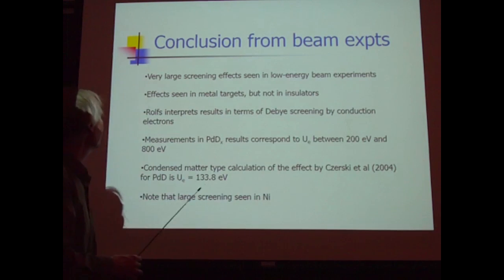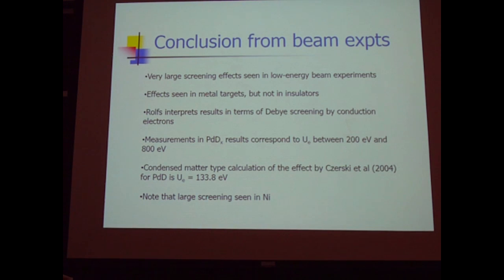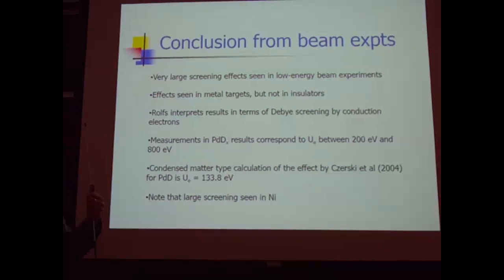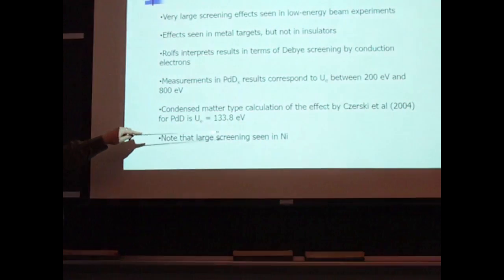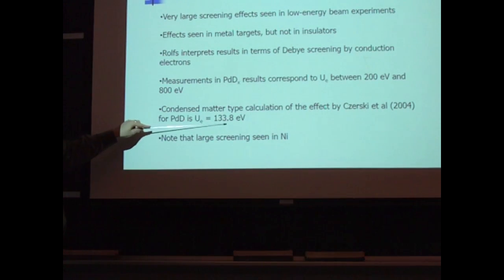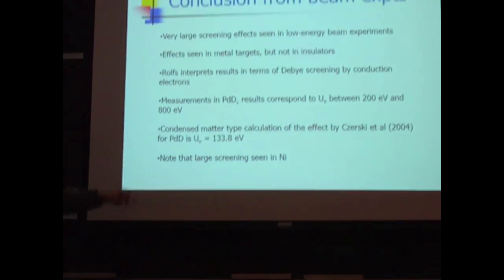So the conclusion from the beam experiments is that very large screening effects are seen. They're seen in metal targets, but not in insulators, and also not in semiconductors. Rolfs interprets this in terms of Debye screening, but I think that there are two issues. One, Thomas Fermi, or more accurate many-body electron screening models, would be more relevant for the static problem. The dynamic problem, I don't think I've seen a calculation of yet. I think the dynamic problem really has to be solved to understand these screening experiments. So somewhere between 200 and 800 from the beam experiments. The Thomas Fermi number in Czerski 2004 is 133.8 electron volts, and also large screening is seen in nickel.